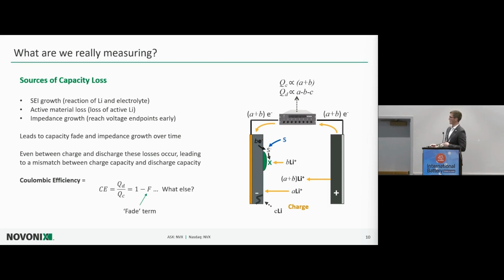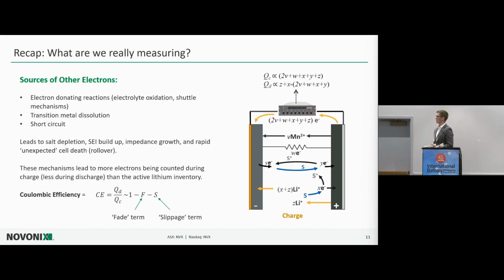And what this eventually does is, I'm going to build up this description of coulombic efficiency here. What this does between the charge and discharge cycle is lose a little bit of capacity, so your discharge capacity is slightly smaller than your charge. So you get this ideal coulombic efficiency of, say, 1, and then subtract this fade term of all of this capacity that we're losing. We're all very familiar with this. Then the question is, what else is happening? What else really matters for degradation mechanisms in lithium-ion cells?